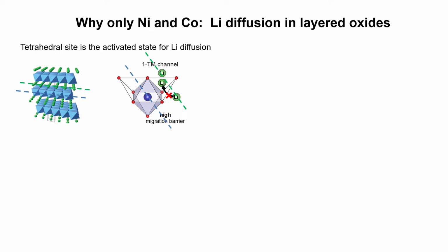Okay, so why is the lithium diffusion messed up? Because in batteries, we actually like close-packed oxide. Density is a very important thing in batteries. And so almost all the relevant oxides are FCC close-packed. They have ABC stacking of oxygen. And if you look at the topology in there, lithium sits in octahedral sites, and so do the metals. But in FCC, it turns out if you want to diffuse from one octahedron to another, you always have to go to a tetrahedron. Octahedral face shares with tetrahedral face shares with octahedral. And so here's an example of a lithium going from one octahedral site to another. It goes through this tetrahedral site, and there it face shares with a transition metal in a layered oxide.